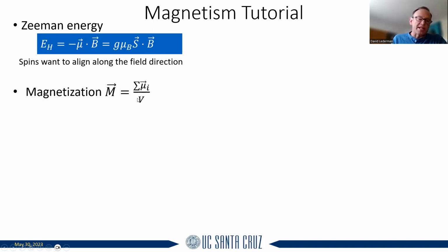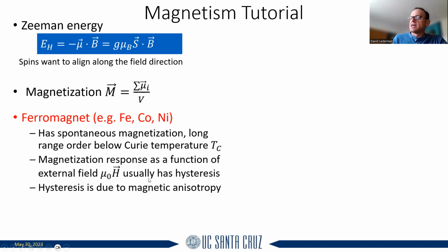We have the concept of magnetization, which is the sum of all of the magnetic dipoles that you have in the system, and as a result of this, you can have a ferromagnet, which is in a field that has a spontaneous magnetization, has long range order below a temperature called the Curie temperature, and the magnetization response usually has some hysteresis due to the magnetic anisotropy that we talked about.